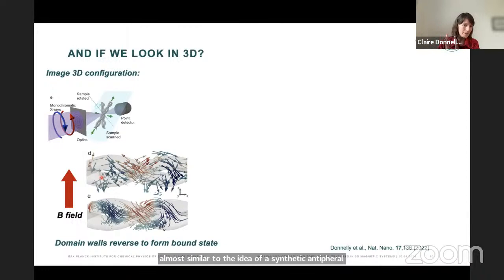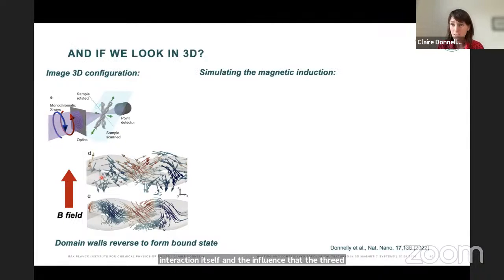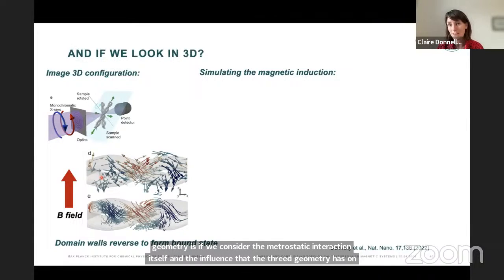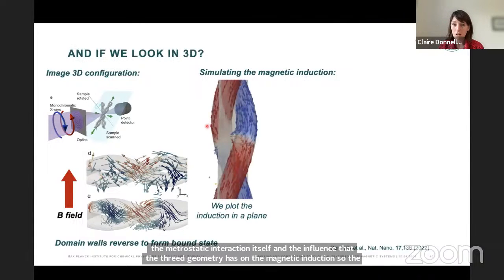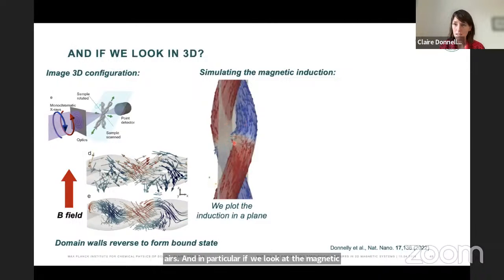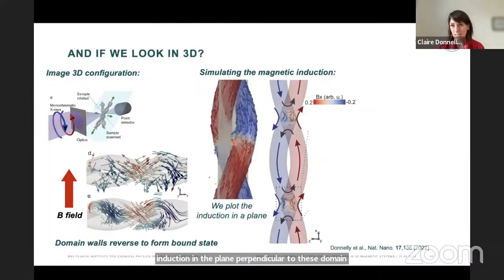But okay, we have, let's say, the magnetic state and the magnetization. Where this gets even more interesting is if we consider the magnetostatic interaction itself and the influence that the 3D geometry has on the magnetic induction, so the stray field surrounding these domain wall pairs. In particular, if we plot the magnetic induction in the plane perpendicular to these domain walls, including both the stray field and the magnetization, we see something quite familiar when we think about our topological mindset.